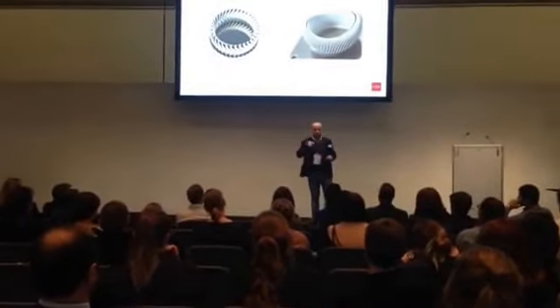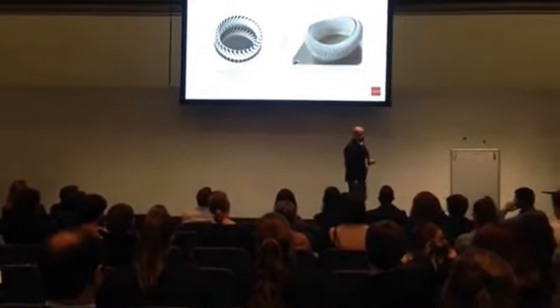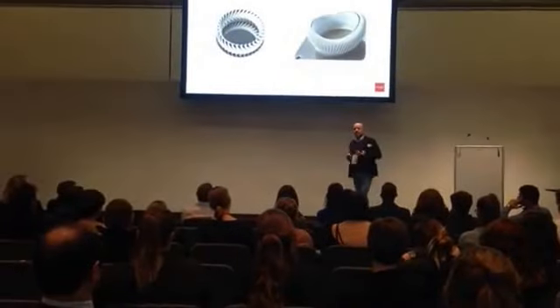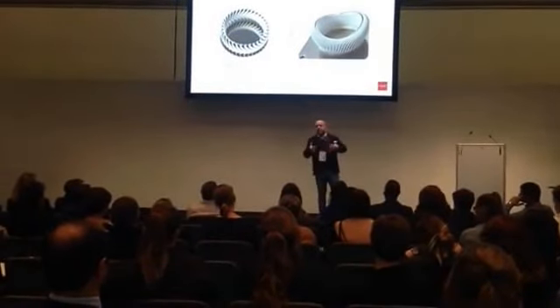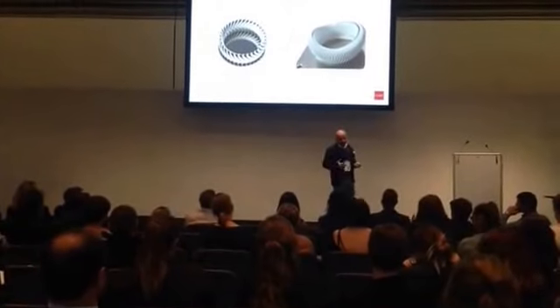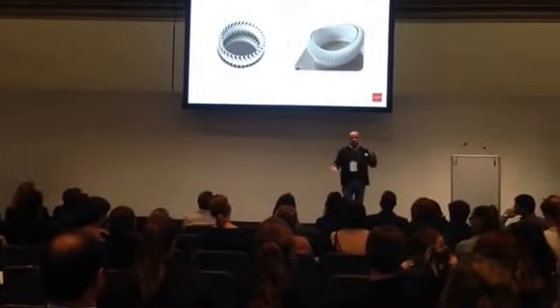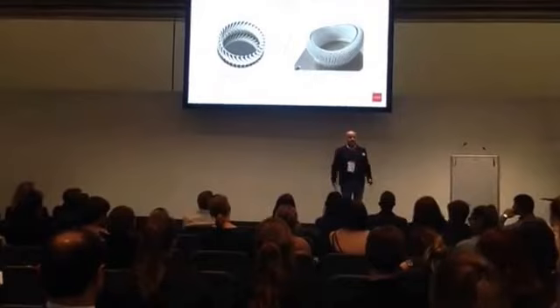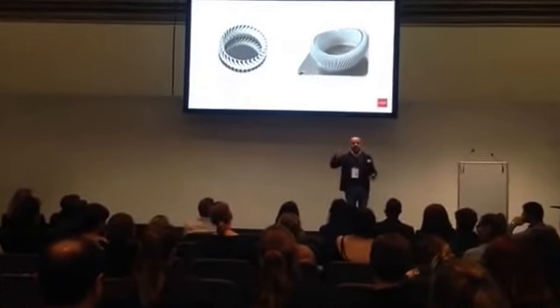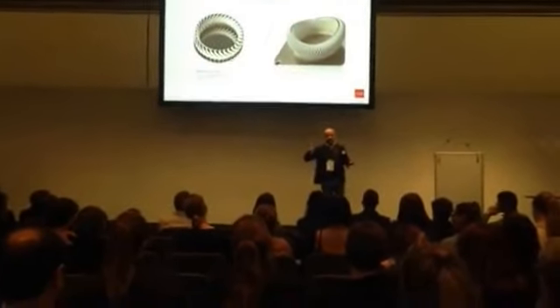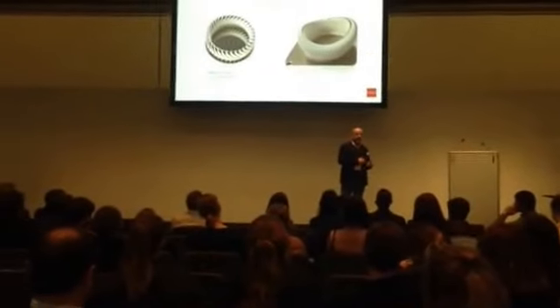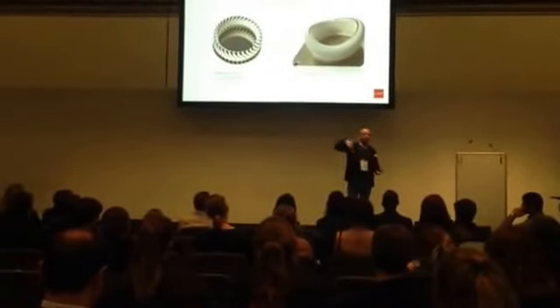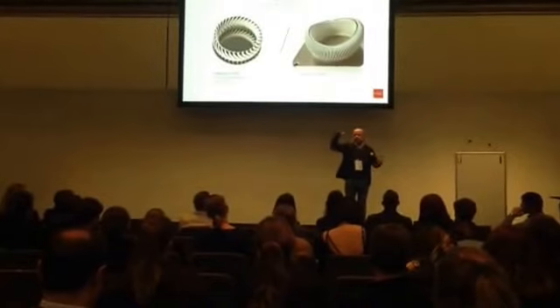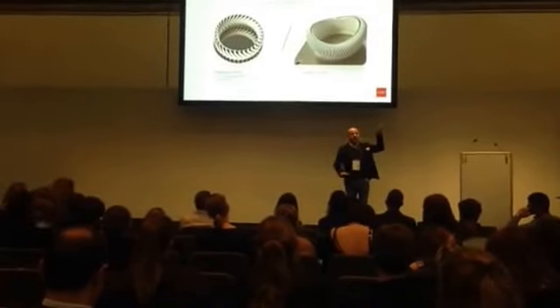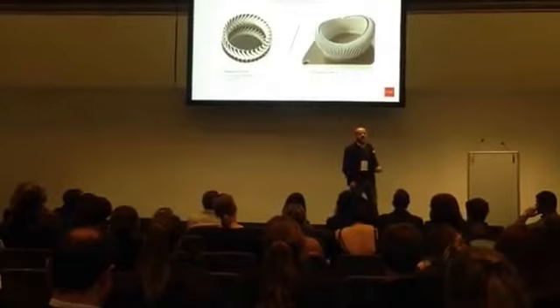In the case of titanium, it's opening a lot of opportunities also because of a very high melting range, but a big complication during casting. If we do a benchmark between casting and 3D printing, we can say that the materials easy to cast are very difficult to print, and the opposite: the materials difficult to cast are very easy to print. So titanium is one of them.